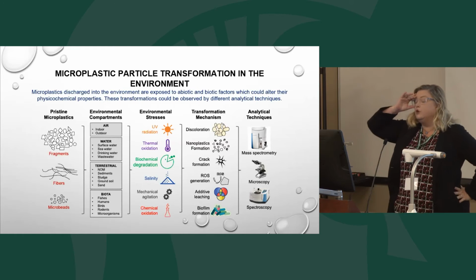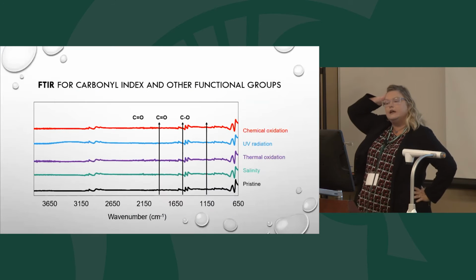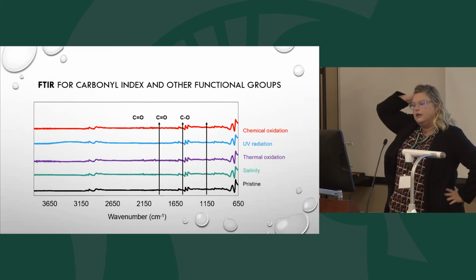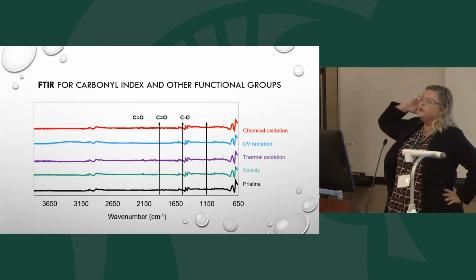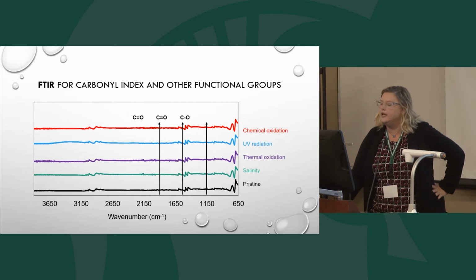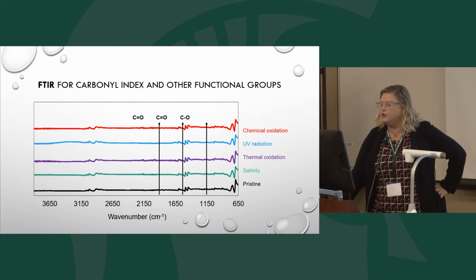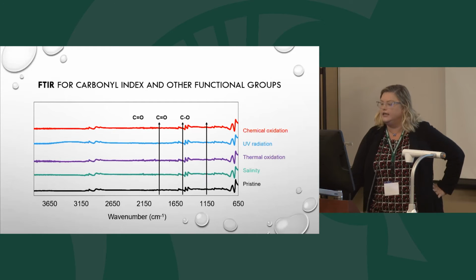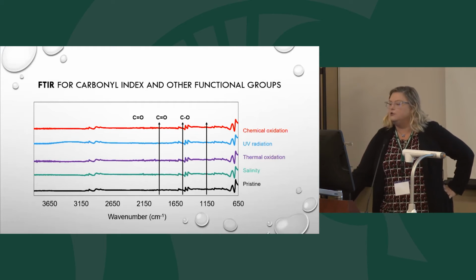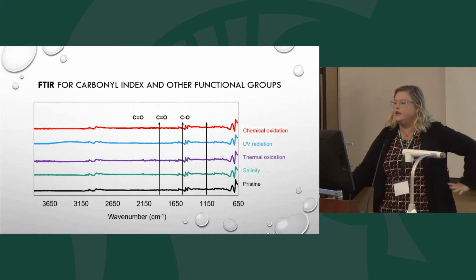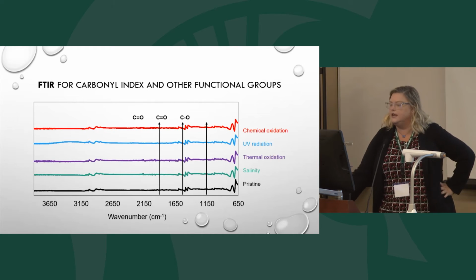Here's an example of the difficulty in finding that carbonyl index. The carbonyl index, you use FTIR to find this particular peak. Sorry that these labels are shifted over, but the arrows are indicating the 3 different wave numbers that you look for for these carbonyl indices. 2 of them are double bonded COs and 1 of them is a single bonded CO. It measures both the stretching and the bending frequencies of each of these particular peaks, and together it'll give you an index.